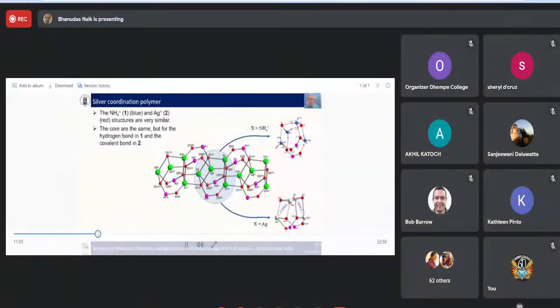Oxygen bridge center here, and these phosphonate groups are here. They join with the organic linker to another chain of these oxygen-bridged silver centers. And you can see that the centers are almost the same. This is the ammonium center. The center here, if you look at it, you can see that it's a tetrahedral center. You have 4 oxygen atoms around that on each side, and you can see that here as well. The hydrogen bonding here, and the silver forms exactly the same way here. And you have about 3.1 to 3.06 angstrom distance between the silver centers, so they're really quite close.